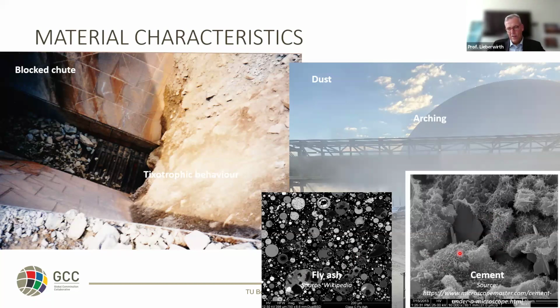Usually, if you take it from the pallet in the do-it-yourself market, it's stiff like a board. If you take a cement which contains fly ash, it slides and it's really fluid. So it is worthwhile to think about it. And if you have this material, and in this case, that was even a so-called, we found later,